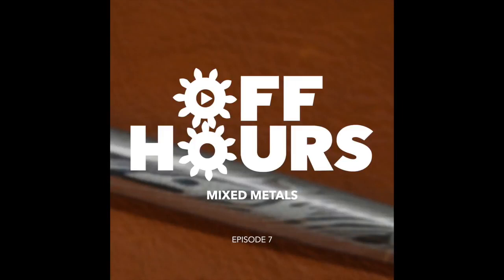When you're making the flask itself and you're pouring the investment plaster in, you want to ensure that there are no air bubbles in the work at all. And so because the investment plaster is quite thick, think of it like a thick porridge when you're pouring it in. You get small air bubbles that attach to the models and don't want to just come off by themselves. It's not like water where it's liquid enough that the air will just come out. I use a vacuum chamber to vacuum out all of the air from the flask.